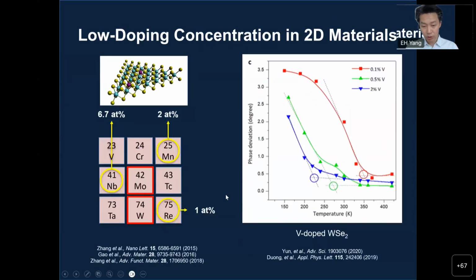One of these papers shows, because there are several, a common question is, what about the doping concentration? What's the percentage of doped vanadium atoms in these 2D materials? It's not high. In our case, it's 0.5%. That is an estimation we got from the XPS result, which I haven't included in this presentation.